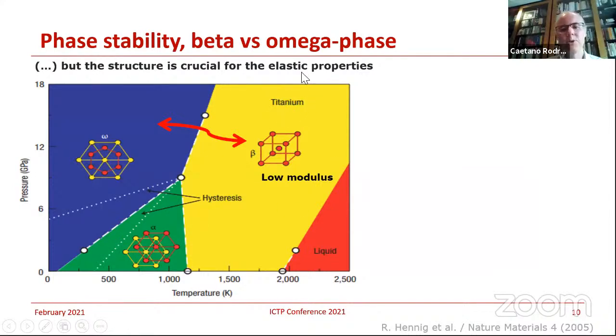And here I show to you the phase diagram of titanium with pressure and temperature, because you have to look for if the structure that you are looking for is really the one that can be stable for a given situation. In this particular case, since titanium is the largest amount in the alloy, you are looking for the beta phase, that is the low modulus one, that is the BCC phase.